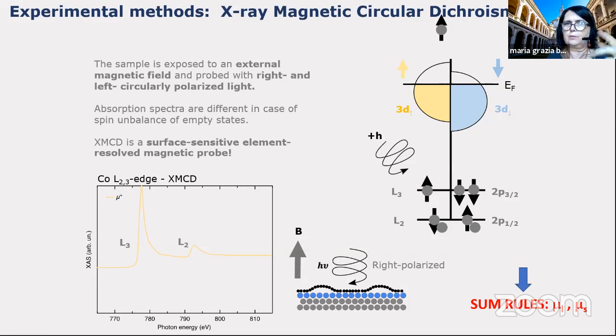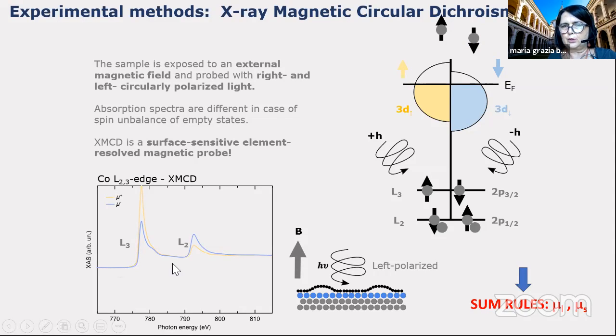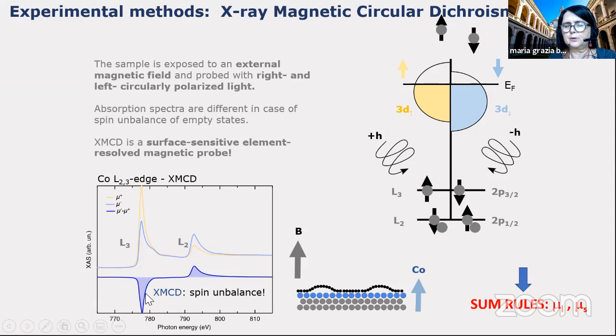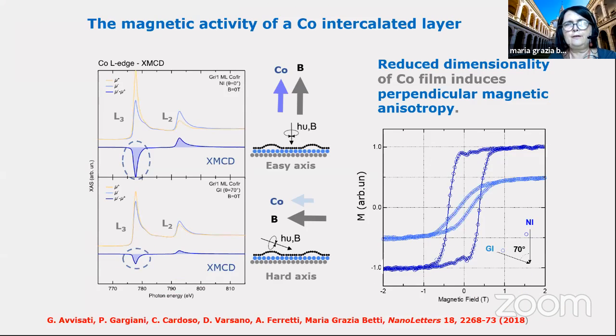And the absorptions are different if there is a spin unbalance. So if you change from right to left polarized light, or if you change the direction of the magnetic field, you will have two different absorption spectra, and the difference between the two absorption spectra is our dichroic signal. This dichroic signal is related by means of the sum rules to the orbital and the spin moment of our system. So this is important because we have a surface sensitive and element resolved magnetic probe. So we can distinguish the response of cobalt or the response of the magnetic molecule on top.